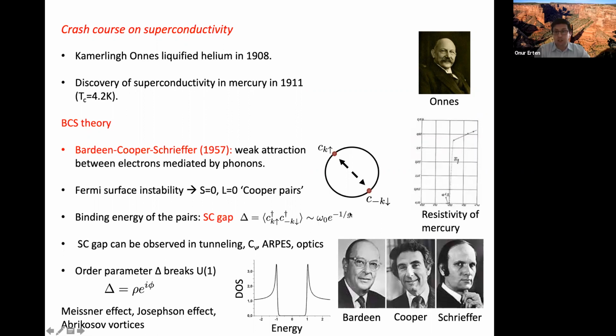So the transition temperature, in BCS theory, is set by e to the -1/g, where g is your coupling constant, something like the density of states times the electron-phonon coupling, and omega is the Debye frequency. This gives you a transition temperature that is proportional to your superconducting gap. Looking at this proportionality, you can say how well your superconductor fits in the regime of BCS superconductors. Small deviations from this ratio tell you it's maybe not exactly BCS theory, but you can do corrections to BCS theory, the so-called Eliashberg theory, which works really beautifully for strongly coupled electron-phonon systems like MgB2, for instance. That gives you remarkably good results.